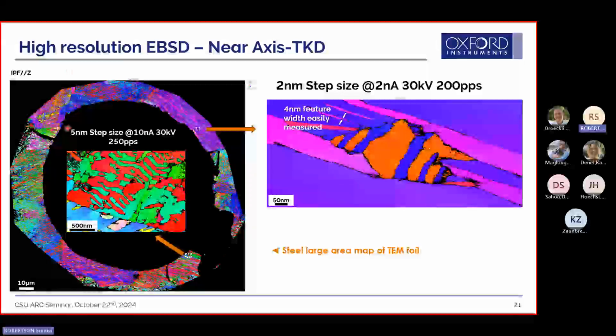So the example data set I have was using the traditional TKD with the off-axis mode, and we were using 5 nanometer step sizes at 10 nanoamps, and now we could go down to characterizing 2 to 4 nanometer features because we could go down to a 2 nanometer step size with the improved geometry. But you don't need to go that far. That's just to tell you how far technology has come these days. And now you can also do EBSD on TEMs with precession electron diffraction. It's different, but again, that's what we can do.